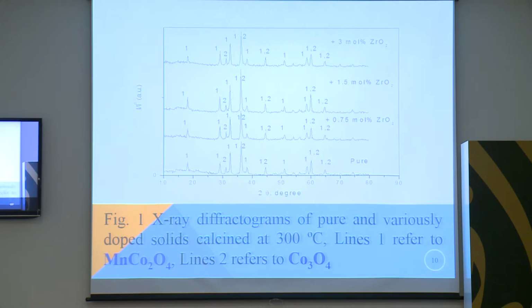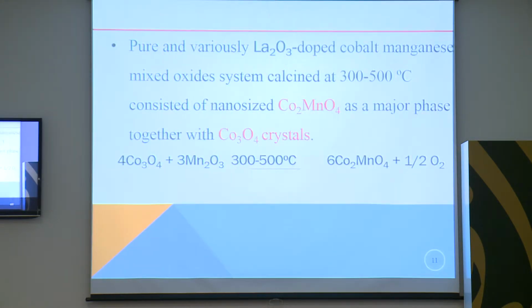This figure represents the X-ray diffractograms of pure and variously doped solids calcined at 300 degrees. From the results of this curve, we can conclude that the lines which appeared refer to the compound cobalt manganese oxide, Co2MnO4, with the unreacted cobalt Co3O4 as in this figure. These mixed solids, manganese and cobalt oxide, formed through the chemical reaction between Co3O4 and Mn2O3 at temperatures between 300 and 500 to obtain Co2MnO4.